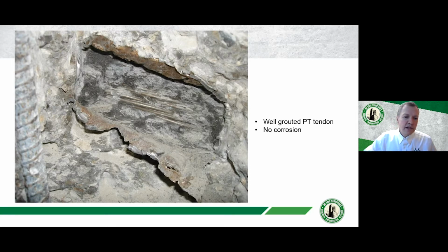In the photograph that you see in this slide, and I'll just get a pointer here, an opening has been made in the side of the concrete to expose the duct. You can see the duct has been opened, a metal duct here, and inside the metal duct the grout has been removed to expose a couple of strands in this tendon. You can see that the strands are in good condition. They've been embedded in good quality grout, and there's no sign of any corrosion activity. This is what ideally we would like to see everywhere.